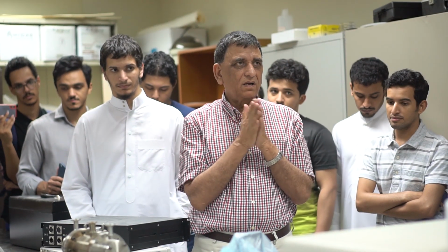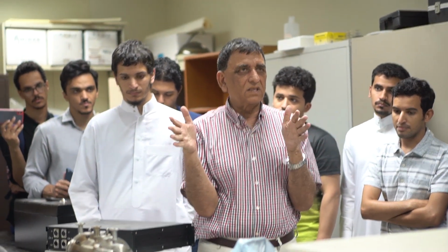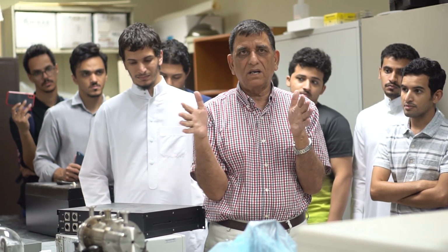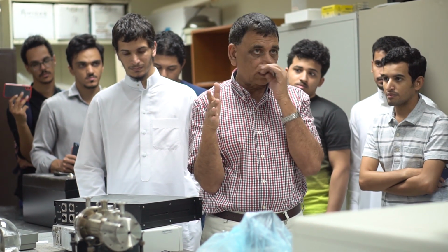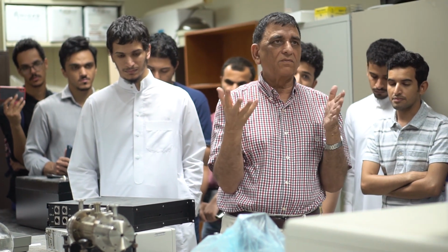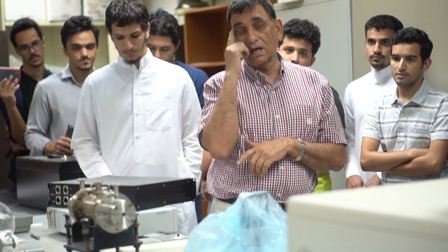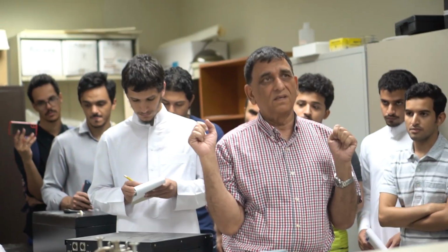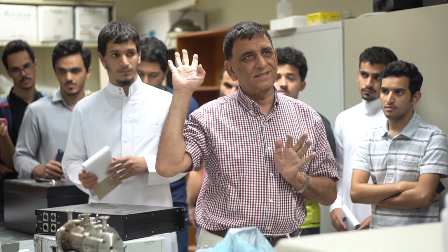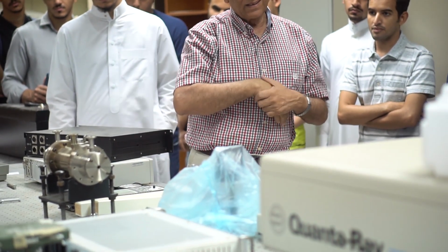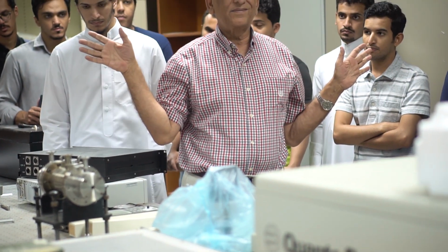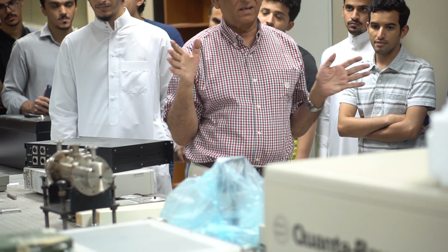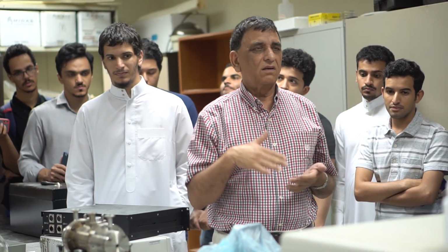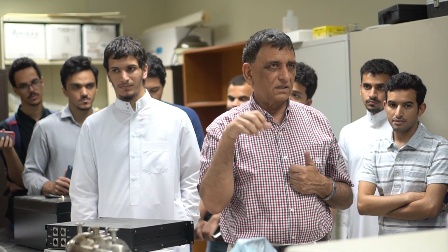But so when we have this 28 kilovolt, we have a breakdown in the gas, so a discharge is created. In this discharge you have a lot of electrons, they excite argon and fluorine, and argon and fluorine become one molecule, which only exists in the excited state. When it comes down, argon is again neutral, fluorine is again neutral and stable. But due to this discharge, we have excited state argon fluoride, but no ground state.